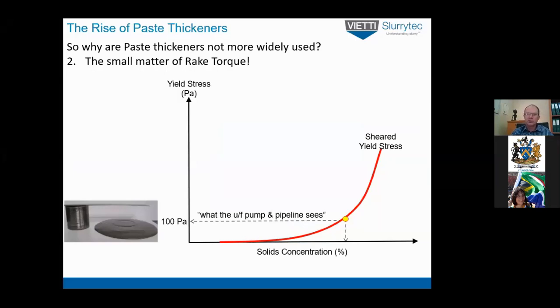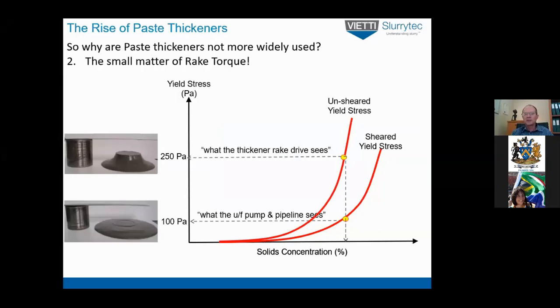So for a typical paste material, it's got a sheared yield stress of about 100 pascals at a particular solids concentration, which would be, let's assume, the design solids concentration. When you look at the unsheared yield stress, that can be at least 2 or 3 times greater, even orders of magnitude greater than the sheared yield stress. So what the rake drives have to see is huge yield stresses, and so the gearboxes have to be really, really strong.